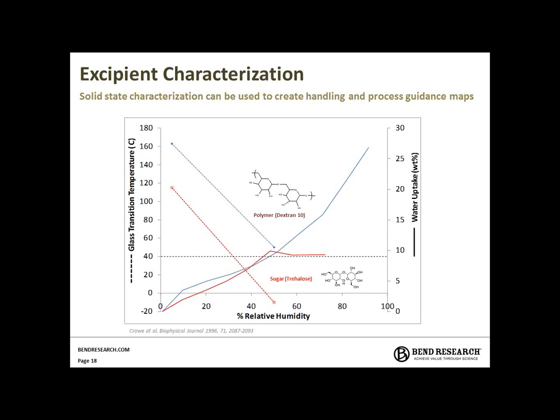What we routinely do is a glass transition temperature analysis as a function of relative humidity in the environment to understand tolerance of the formulation in the face of RH. Along with that, we'll often perform vapor sorption assays where we look at water uptake in our formulations and understand how that impacts the properties of the excipients. In this case, you can see the sugar, trehalose in this instance, crystallized out at around 50% RH. So these are important guidance maps we often talk about with our clients, so they can understand downstream handling and processing of their powders so they don't negatively impact performance and application.